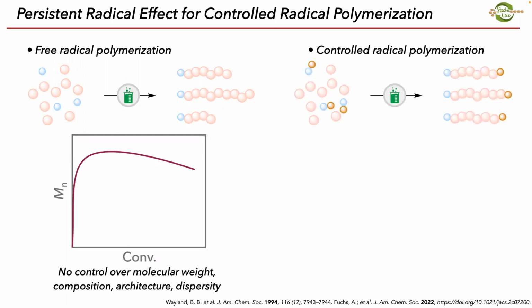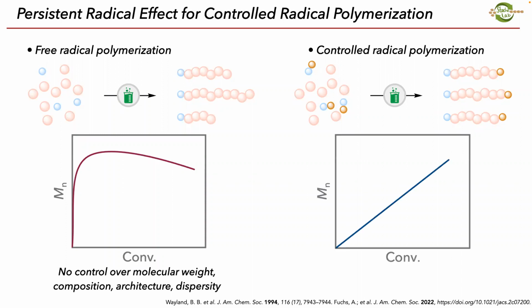So instead, what we've done for the last 30 years is develop controlled polymerization strategies, where we can use some sort of reversible deactivator so we can keep our radicals, which are highly reactive, at a low concentration. And now we can get uniform chain growth. So all of these polymer chains are now the same length. Molecular weight increases linearly with conversion. And so as we consume the monomer, we grow the polymer chains at a uniform rate.